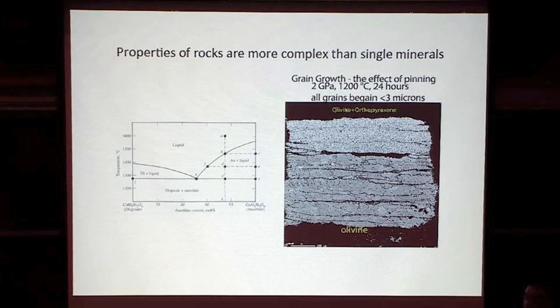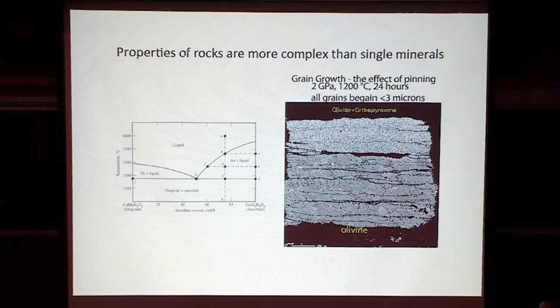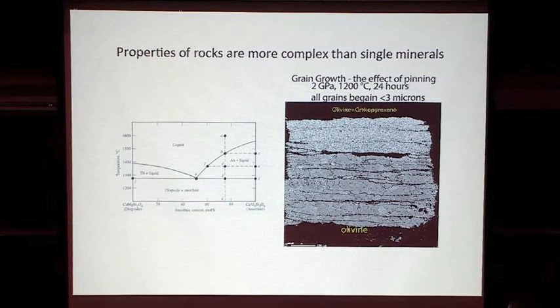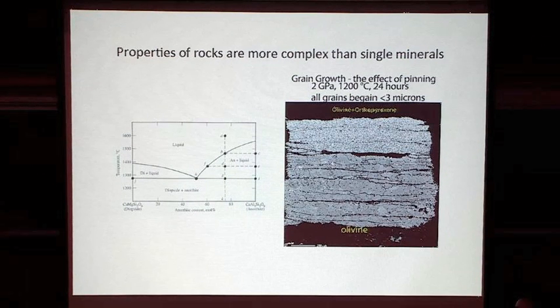So I have a comment about what stops grain from getting very big. I remember there's also another effect when you have perovskite formation. You have the olivine composition going from ringwoodite and then decomposing to perovskite and ferropericlase. There's a grain size reduction effect. And if you have subduction or a plume rising or crossing the transition zone, then there is a strong effect of reducing grain size. That's in addition to the thinning and the deformation.